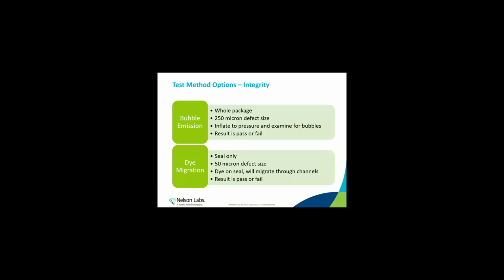The integrity component is perhaps the most vital one, and it would be very hard to justify less than 100% pass rate for a sterile package. For a bubble test, the whole package is tested, and the method can reliably detect a 250 micron defect. The test is run by inflating the package underwater to a set pressure and looking for air escaping as bubbles. For the dye test, only the seals are tested, and this method can reliably detect a 50 micron defect. The test is run by placing the dye on the seal and visually looking for it to pass through a channel. Let's look at the bubble video.